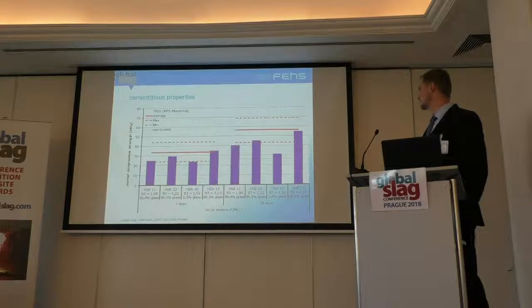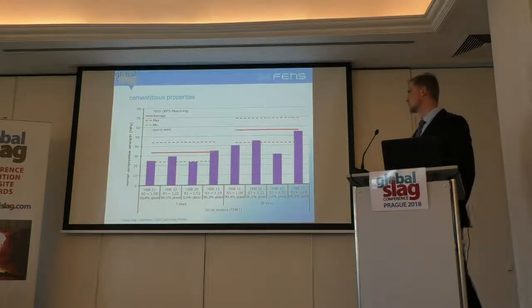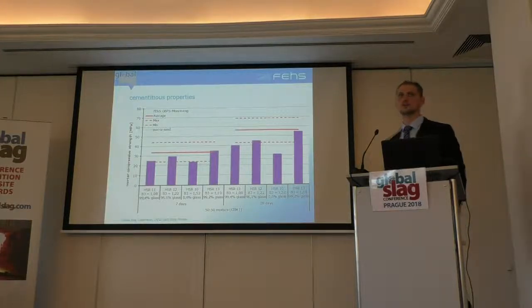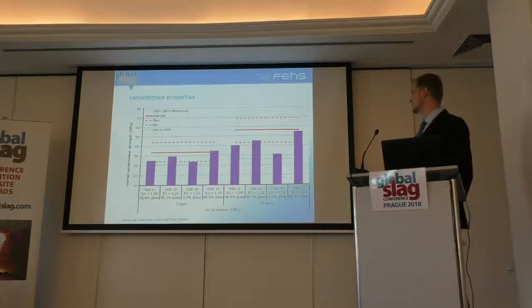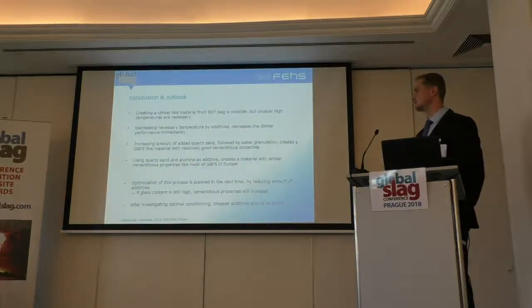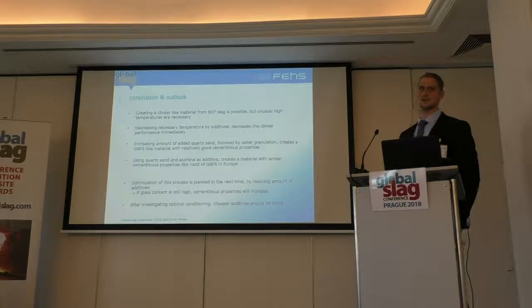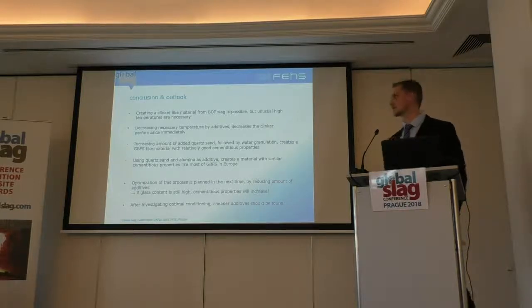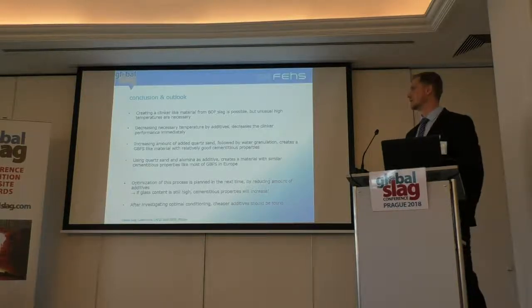So we can see here, just with this trial, we are in the average of the Western European GBFS, that are more or less good values, especially because we didn't really make a lot of trials to optimize the slag.